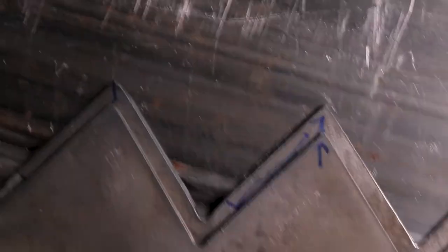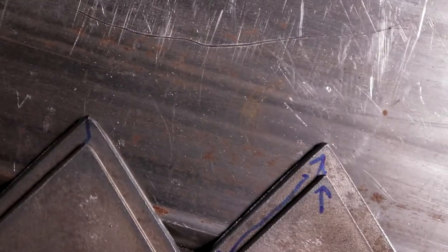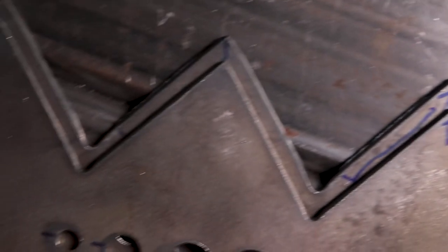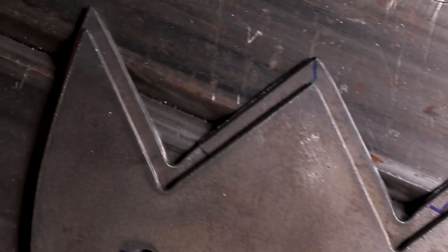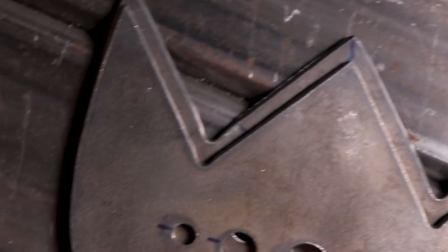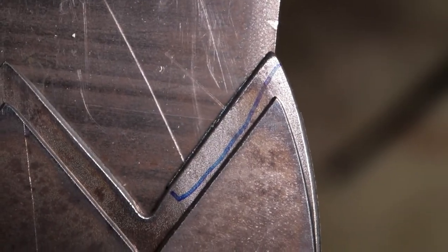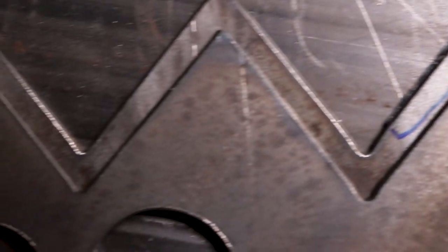Another thing that I noticed when I was taking a closer look at the 14 and 16 gauge samples was I was having an angularity issue. If you take a close look, I'm gonna put the 14 and 16 gauge pieces next to each other, you'll see I'm talking about a bevel that seems to be pretty prominent on the 16 gauge piece and the reason I think that happened is something with the position of the jet actually not sitting directly in the middle of the plane of where the metal is.